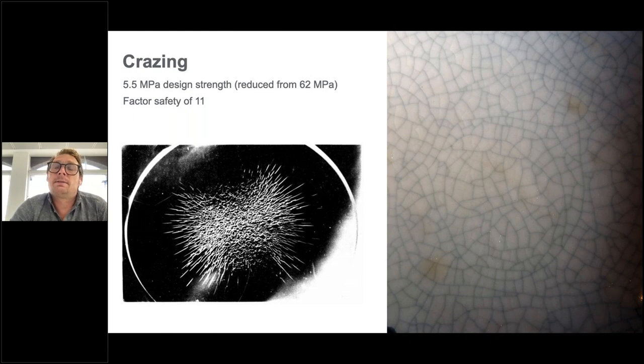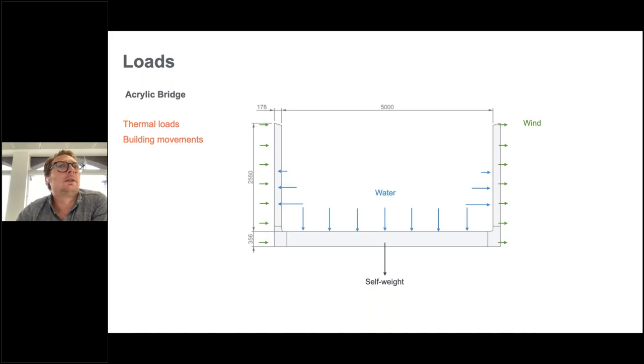So this isn't necessarily a failure of the material. It's a phenomenon that happens at the surface. And this is more of a visual defect. And so also the client would like to avoid the visual defects. So from a short-term load, which we might be able to work to 62 megapascals, we're actually working to a long-term load of 5.5 MPa. And of course, with the water being permanent, that was a dominating load case. But if we looked at the other loads, they weren't insignificant.